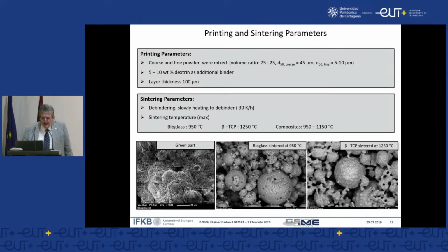So here you can see the green parts on the fracture surface, and in the middle there is a bioglass material after sintering at 950, and the beta TCP sintered at a higher temperature, 1250. It is a relatively porous, weak structure. So at the very beginning we thought, oh my God, with such a weak structure we shall never fulfill the requirement, but fortunately that was not true.